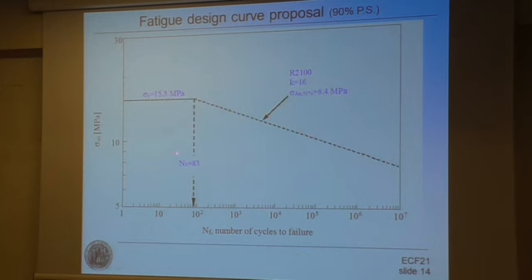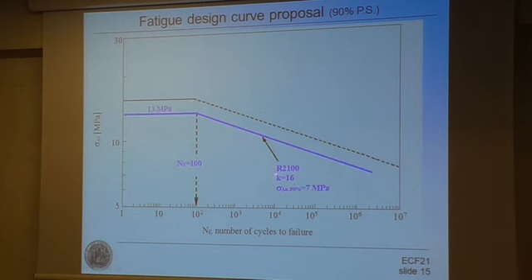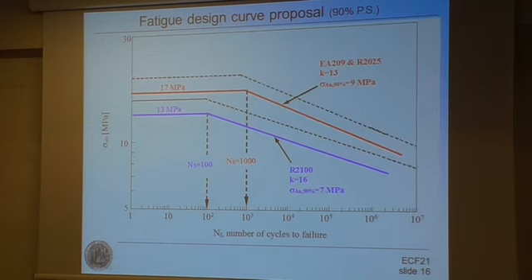Similarly, in the case of totally recycled polypropylene, this is the 90% survival probability fatigue curve that was downgraded, with the aim to calculate the reference fatigue strength at 90% survival probability and 2 million cycles, that is equal to 7 megapascal. And then we have cut the low cycle fatigue zone with a reference fatigue strength evaluated at 100 cycles, that was equal to 13 megapascal. Therefore, two different fatigue curves were proposed. One for compound made by virgin polypropylene, and the same curve for partially recycled polypropylene, but a different fatigue curve that is downgraded with respect to the red one for totally recycled polypropylene.